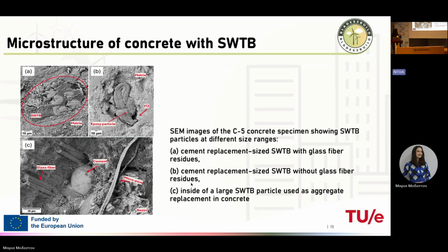And for microstructure, you can see some images of concrete with maximum dosage of wind turbine blade waste. Here we can see some epoxy particles, we can see the matrix, we can see this transition zone. We can see some fibers, glass fibers and cement particles. So indeed, it's really heterogeneous material. And inside, larger particles serve as aggregate replacement. So fibrous particles serve as reinforcement.